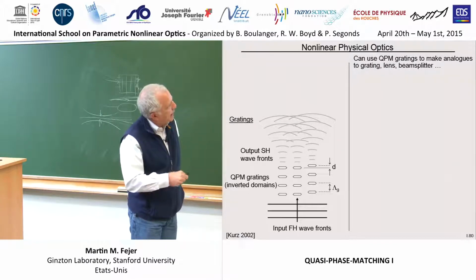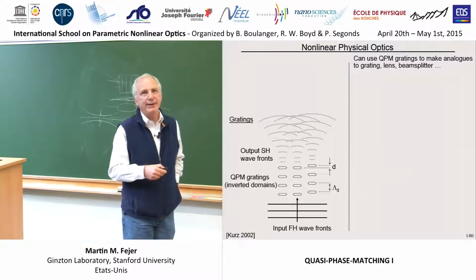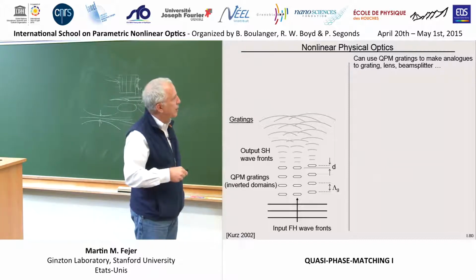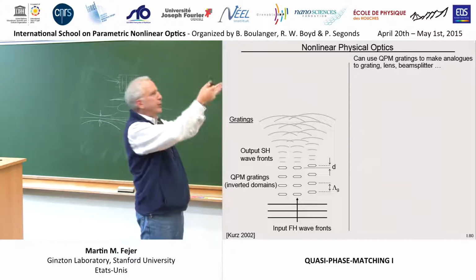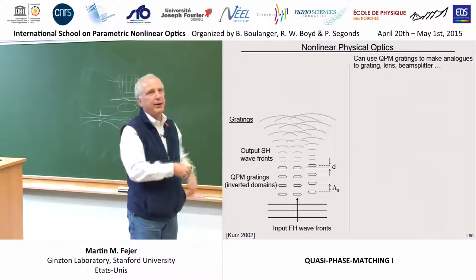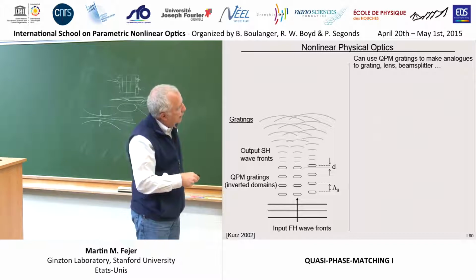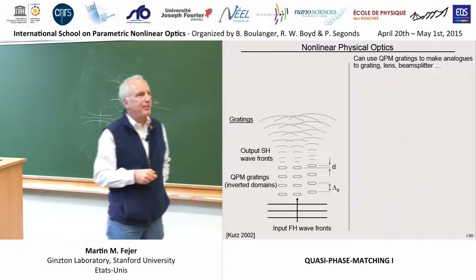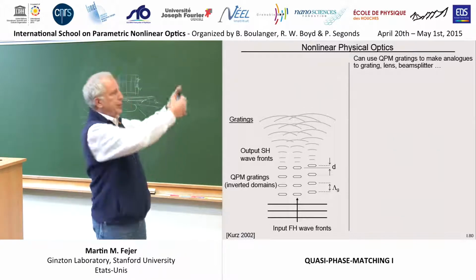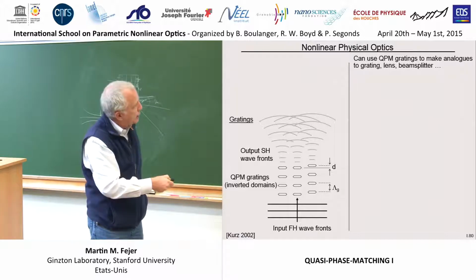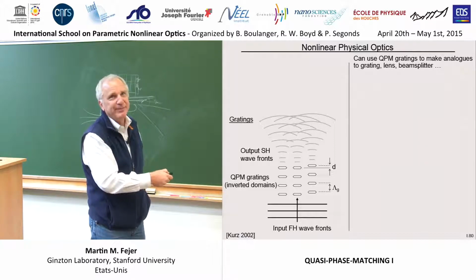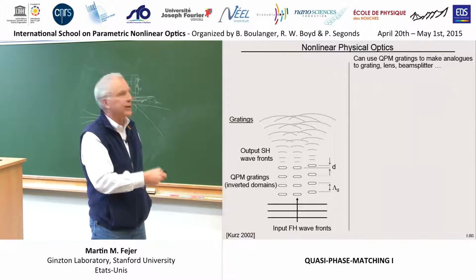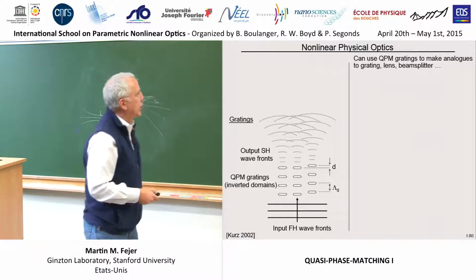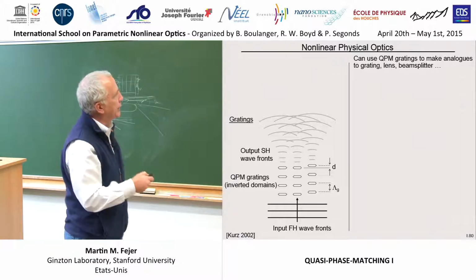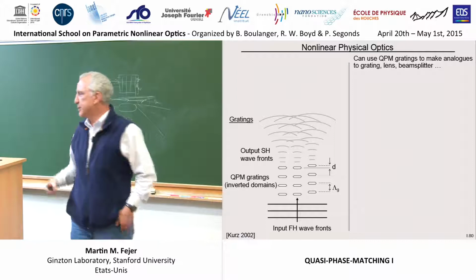So it looks sort of like a multi-slit diffraction pattern, right? If I had just put opaque barriers and let the fundamental go through, I would have seen a diffraction pattern in the fundamental. But here, it's a diffraction pattern in the second harmonic. And by shifting the position of these gratings, of course, you can control the relative phase of this arm versus that arm versus that arm, right? Because the phase depends on the phase of the QPM grating. So what you would expect to see out here is some kind of interference pattern like a multi-slit interference.